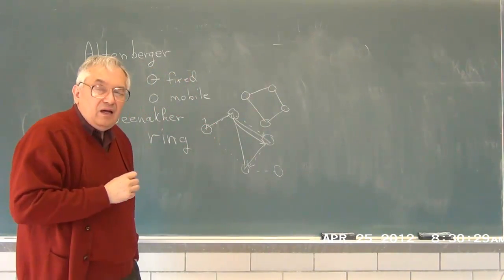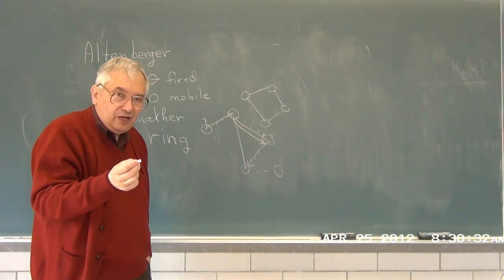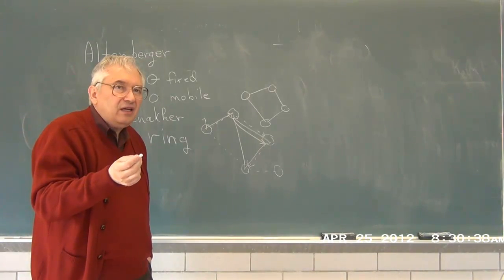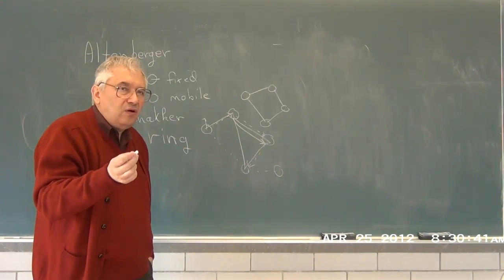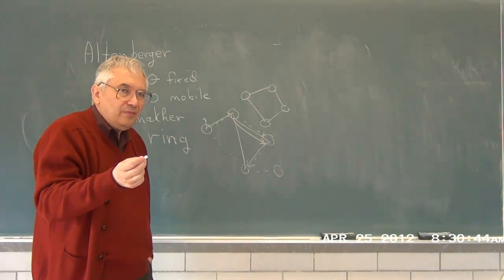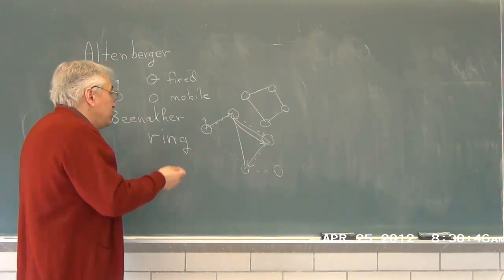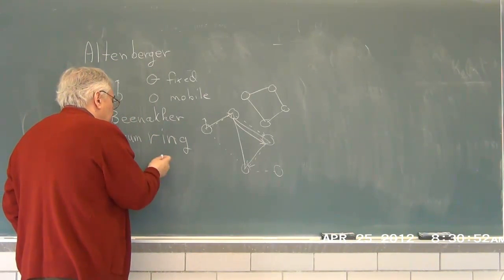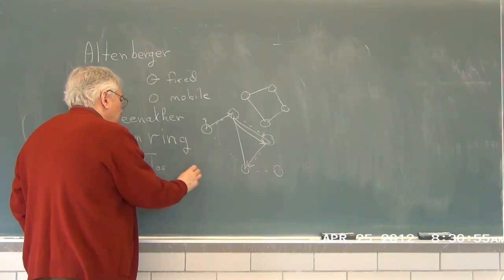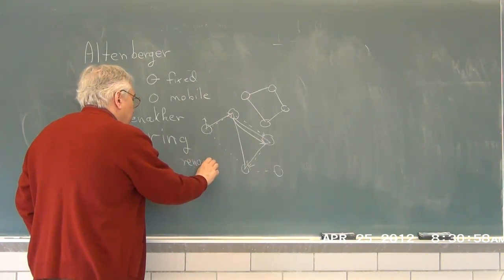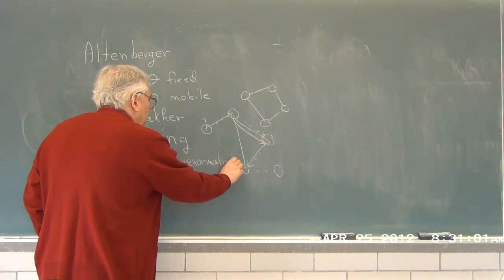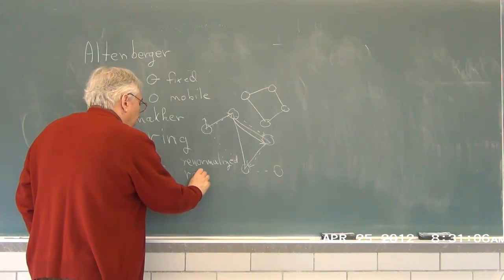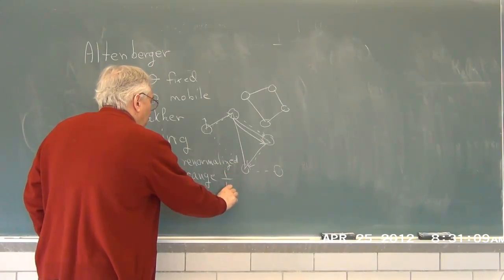Yes? These are the longest range diagrams. The ring diagrams, if you do the electrostatic calculation, are the diagrams that cause screening. They're the longest range part. Well, he resums the ring diagrams. Very clever work. And what he finds is that the Oseen tensor is renormalized. That is, the strength of the hydrodynamic interaction is changed by all of these scattering effects. However, the range remains as 1 over r.